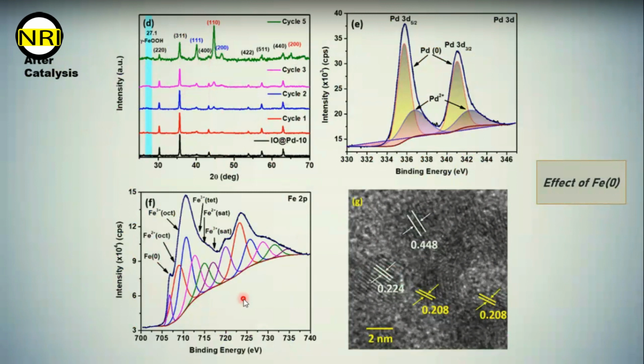And this is the Fe XPS. You can see one shoulder peak at 706.7 electron volts along with the other Fe3O4 peaks. This shoulder peak is due to the Fe0, iron 0 nanoparticles. And another proof of iron 0 is from the HRTEM images, where the lattice fringes of 0.208 nanometer are due to iron 0, along with palladium lattice fringes. So all this characterization proves that iron 0 is formed during the hydrogen generation reaction.